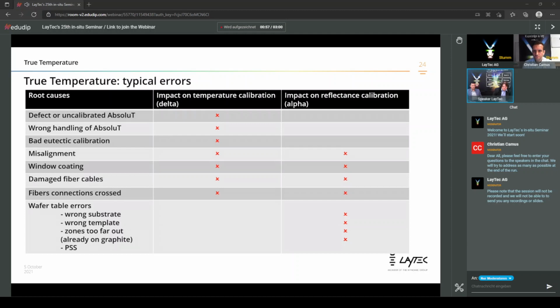Sometimes we see that measurement zones set to the outer zone of the substrates are placed way too far out. So there is a certain risk if you place a measurement zone right at the edge of the substrate, that it can collect too much measurement data from the edge exclusion zone of the substrates, and even in very rare cases, we have seen that even part of the graphite is already contributing to the signal of that measurement zone. So depending on the amount of this impact, it can have even a severe impact on the complete averaging of your true temperature of that zone averaged across a full rotation.